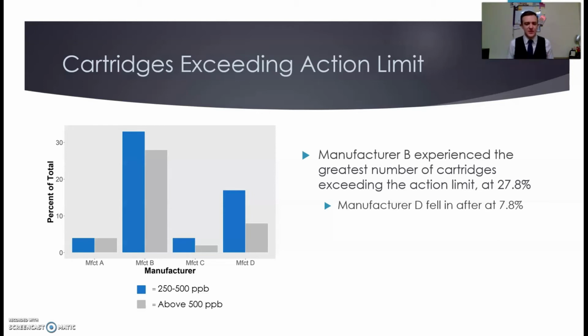And it really starts to illustrate the tremendous amount of manufacturer variation we were seeing, with manufacturer B clearly faring the worst out of the four we tested, followed by manufacturer D, and then A and C falling in at about the same level. So this definitely starts to show that what manufacturer is used in the construction of these cartridges does play a role, and that certainly their process and the way in which they construct the cartridges does play a significant factor in determining how much nickel is leached into the product.